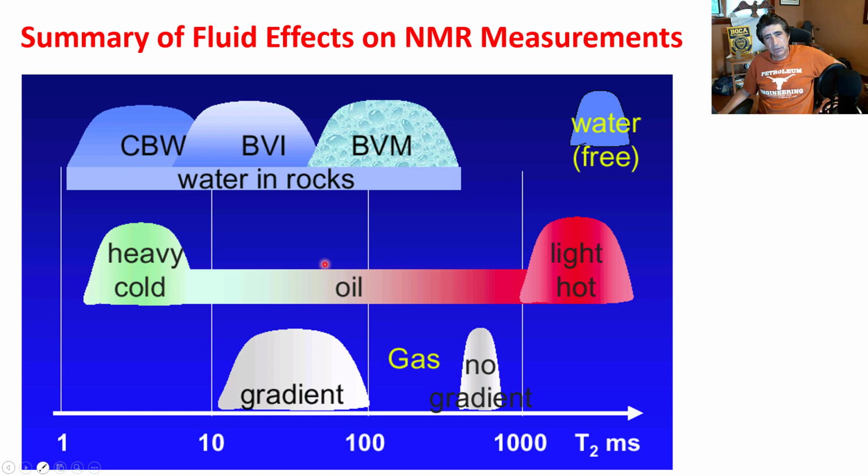This plot is done assuming that surface effects are similar to those of a clastic rock, that is, when the grains are mostly composed of quartz. If the rock were composed of limestone, then essentially we will experience a shift toward slower times, because in some of these rocks and carbonates, the controlling effect of surface is smaller because the density of paramagnetic materials tends to be lower than in the case of clastic rocks.